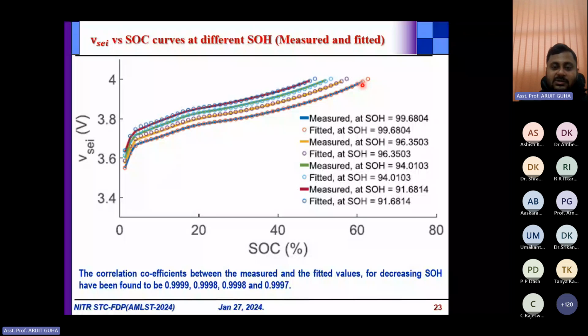So if you think that this is the SOH 99%, this is the first graph, the blue one and the dotted one. After that, the yellow one, which corresponds to SOH 96, is the second one. As the battery health is gradually decreasing, you can see there is a shift. There is a shift that we have observed before also: the Vsei layer voltage shifts to the left side due to the effect of aging. Vsei has reached this voltage when the SOC was much less compared to when it was around 99%. Here the battery SOH is 91%.